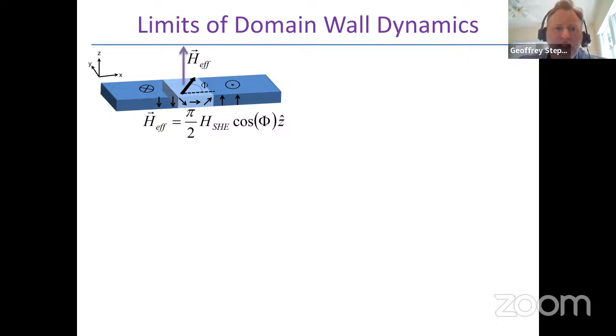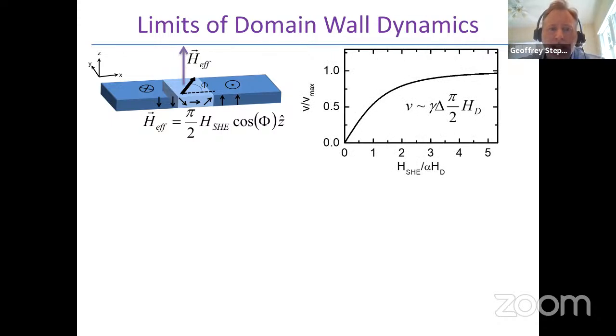And because it is that internal restoring torque, there is a fundamental speed limit for spin texture dynamics for domain walls. And you can see this. If the wall wants to be Néel, then the furthest you could distort it from being Néel would be to make it Bloch. And that's the maximum restoring torque that you have. So that's the maximum velocity that you can get. With spin orbit torques, you'll never drive it beyond 90 degrees. So there's a plateau in the velocity. And that velocity is proportional to the domain wall stiffness.